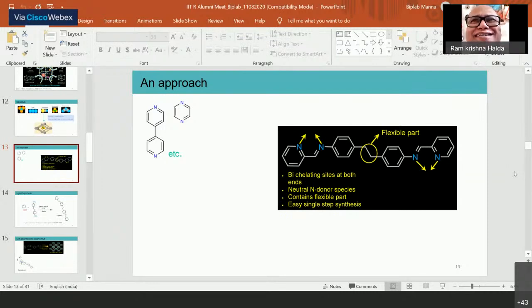You are into basic research, and I'm talking in terms of application research. So I've done some experiments on its ability to store gas, say LNG, so that it can become a future transporter of LNG and we can store it. That can be possible. But we checked nitrogen and CO2 adsorption, yes. But it was very weak because, as you see, the structure is very squeezed after losing the gas molecules. So at the structural level, the gas adsorption capacity of this framework is very less.